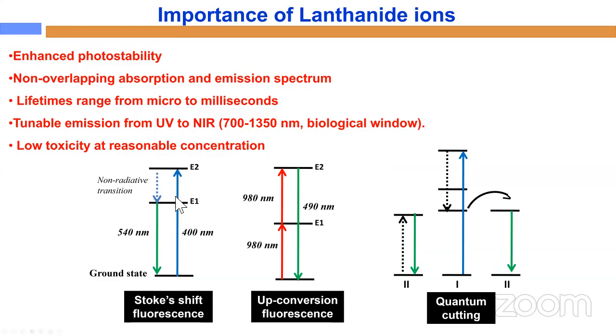The next one is the upconversion fluorescence, where you excite with low energy photons, but you get one higher energy photon. For example, the middle one: you excite with 980 nanometers, the electron from the ground state goes to the excited state E1. Because of the enhanced excited state lifetime, it can take another photon from the laser or through an energy transfer mechanism, which I am not going into detail on, and go to the next level E2, and then you get one higher energy photon. Here the theoretical quantum yield can be 50%.